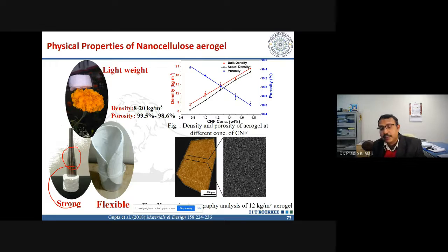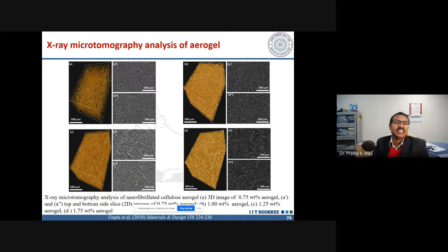For the aerogel, we have checked whether there is any defect or not, using a CT scan image. It shows there is no deformation inside the material. This is the X-ray microtomographic CT scan image, a three-dimensional image of our material.